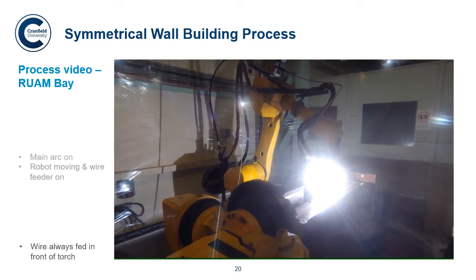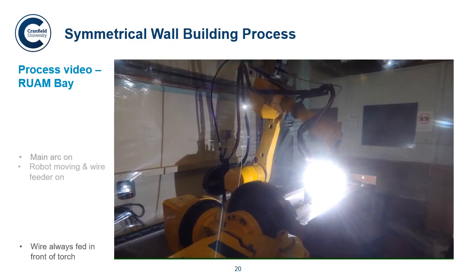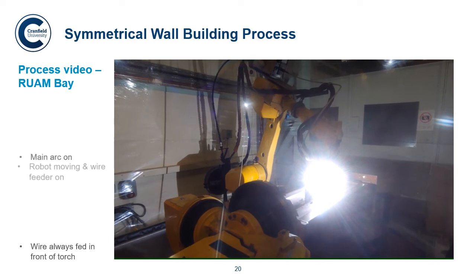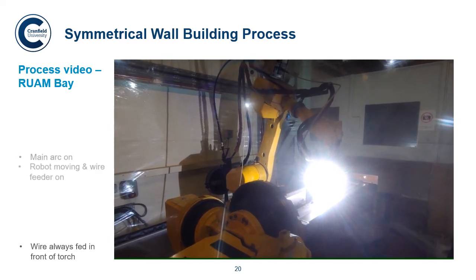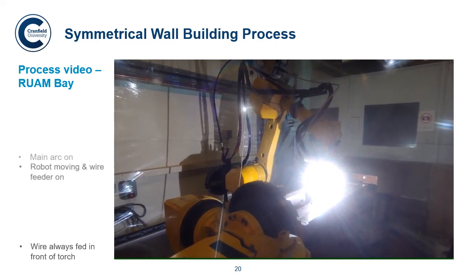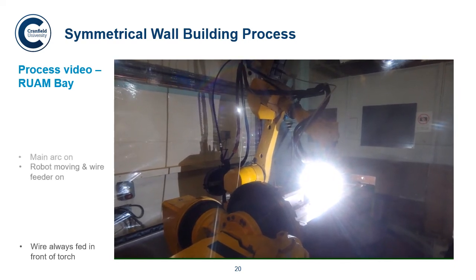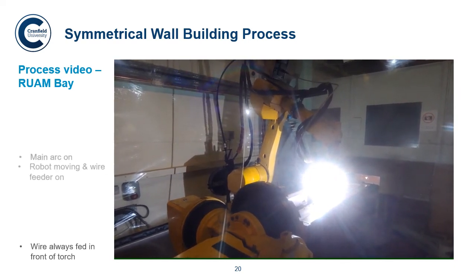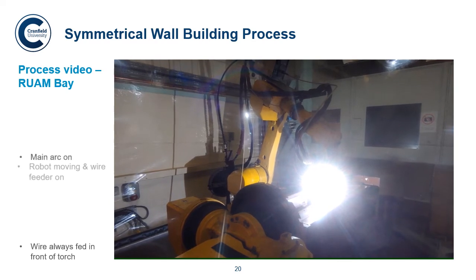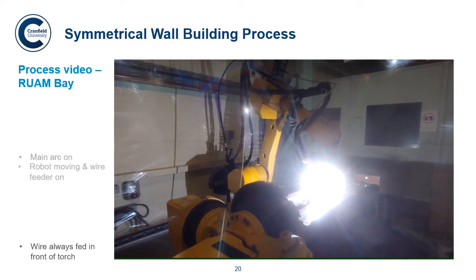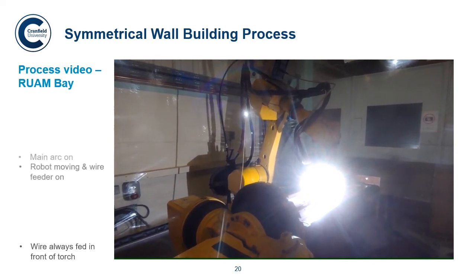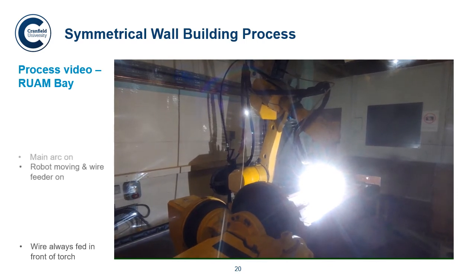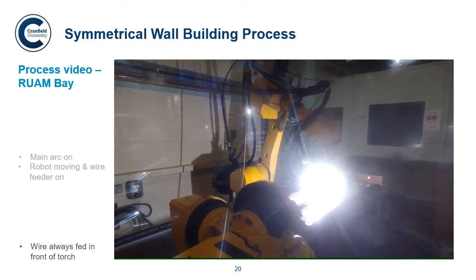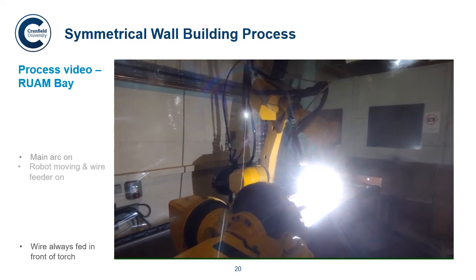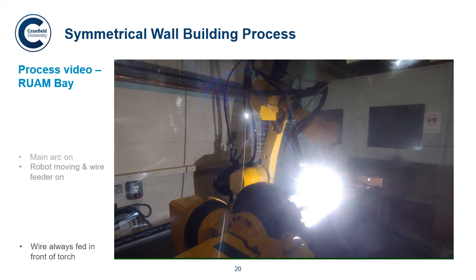The benefit of depositing on both sides of the substrate is actually to cancel out some of the residual stress that you get from depositing the alloy onto the plate. And it also helps speed up your production time, makes it much more productive as you finish welding on one side, your cooling can take place on the other side while you're continuing the process on the opposite side. It's actually very good for increasing productivity.